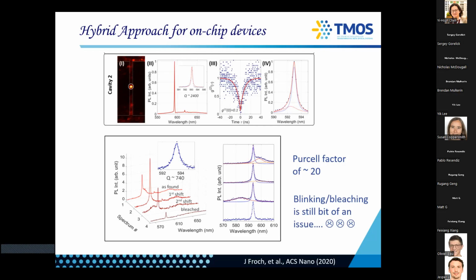The challenge is, of course, blinking. What we found along the way in this journey is that emitters on silicon nitride actually blink a lot. And the same thing happens on any silicon-based substrate. We don't actually know why. We tried capping and stuff, it doesn't really help, and we cannot cap underneath, remember, because the cavity is coupling evanescently to the emitters. Our emitter should really be close to the cavity. So we don't really know what's happening, but this is one live result.